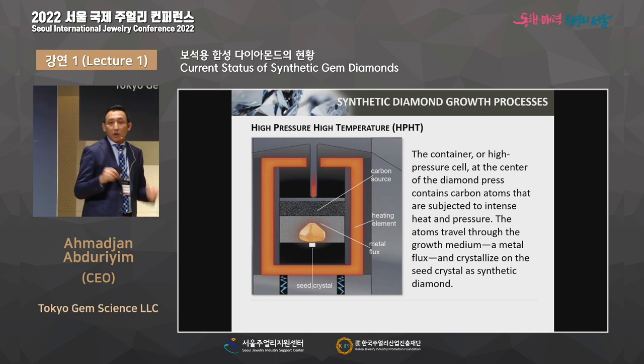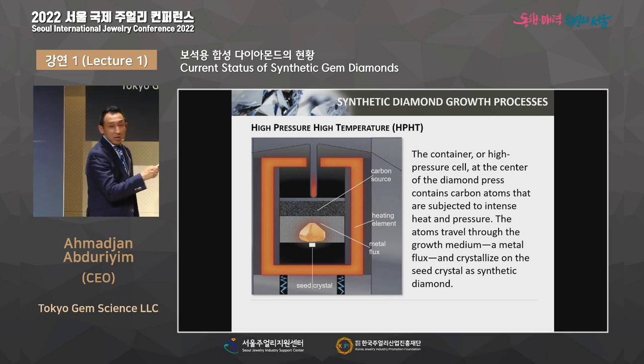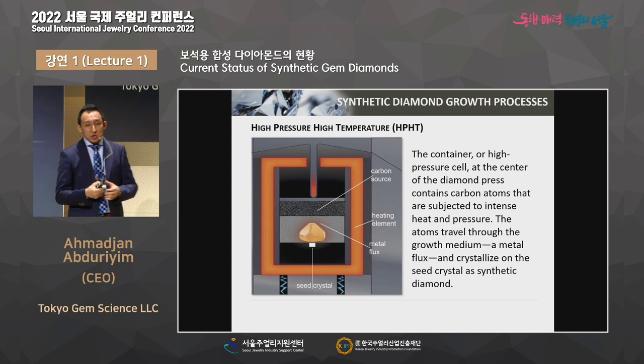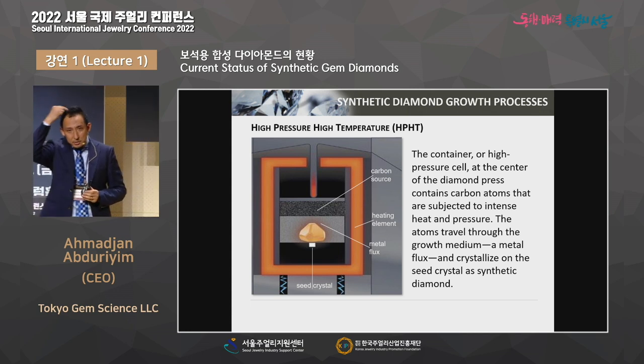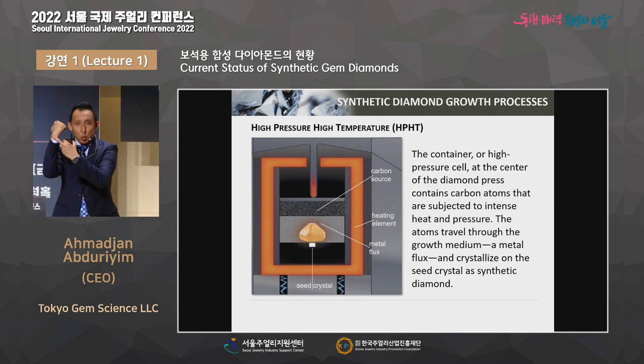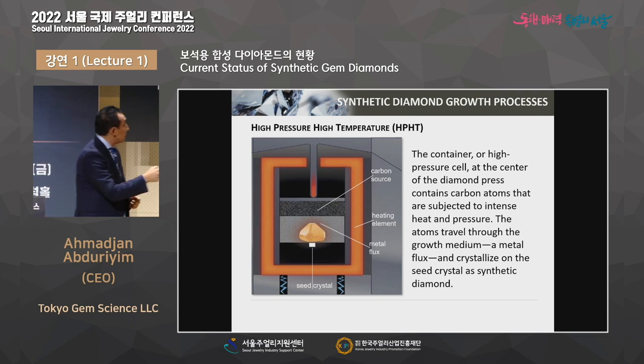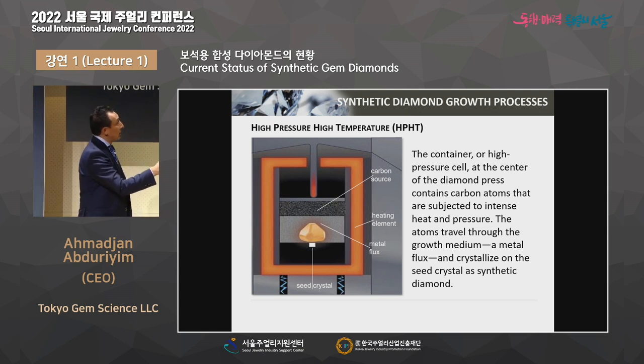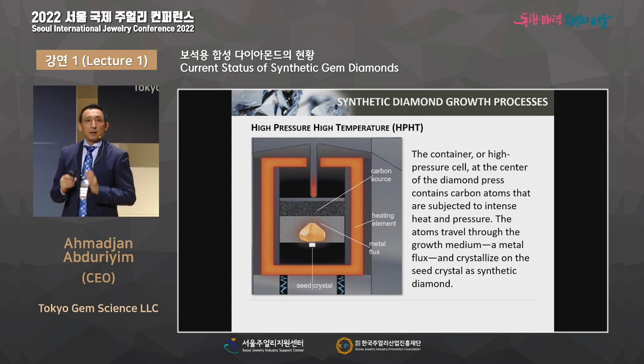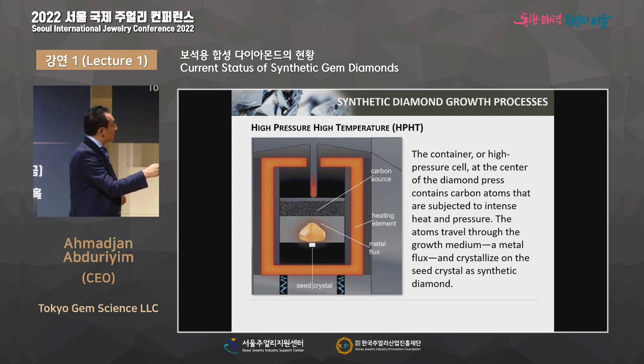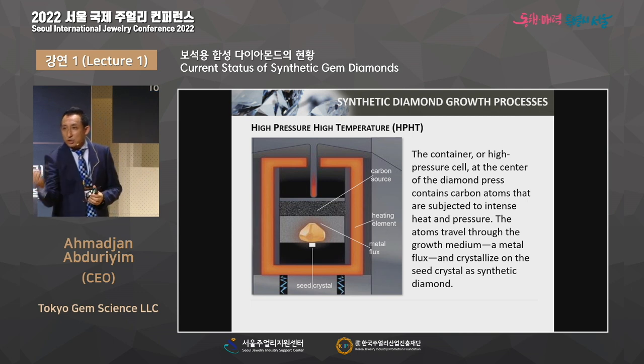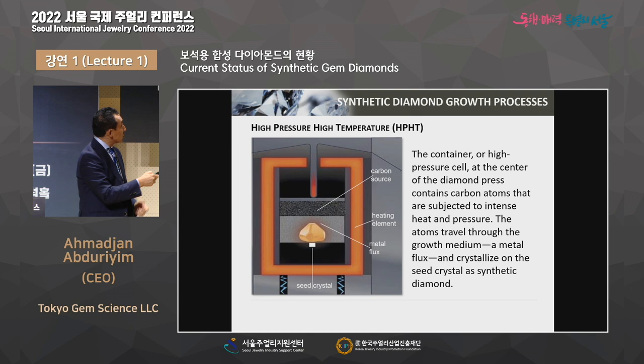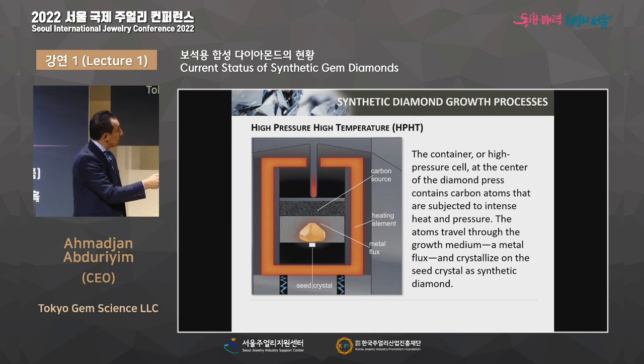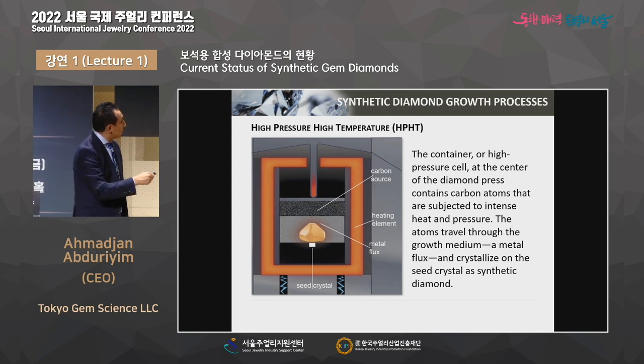Here, the first one is graphite. As a source, you need to use very pure graphite. Sometimes it's made from natural graphite, sometimes from your hair, sometimes from your bone. They need very pure carbon. And second, here we have the metal flux. As I explained, iron, nickel, cobalt, the liquid situation is here. And we put one seed crystal at the bottom. So the carbon is heated and pressurized, and it can become the liquid phase of the carbon and gradually crystallize on top of the seed crystal.